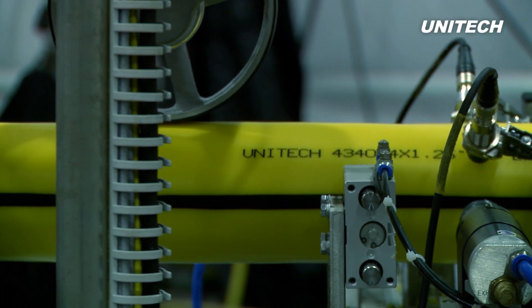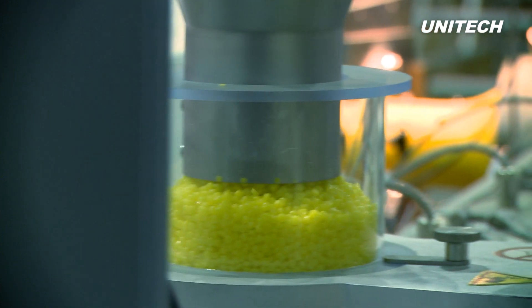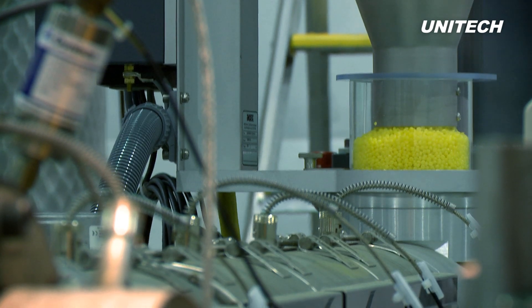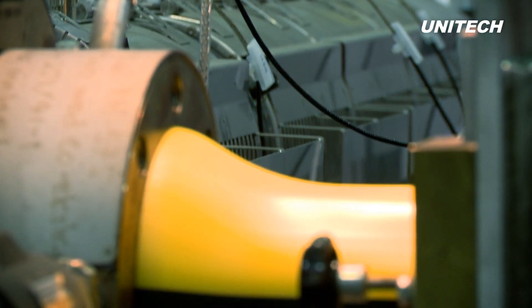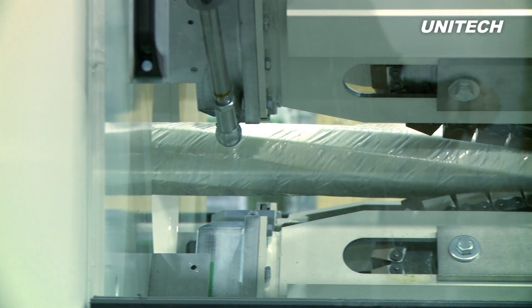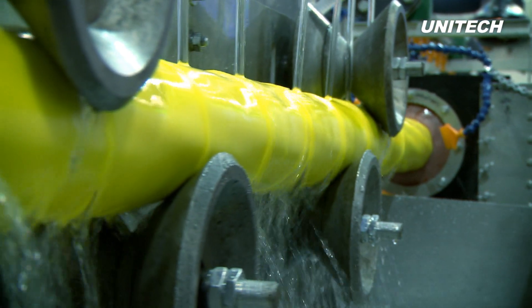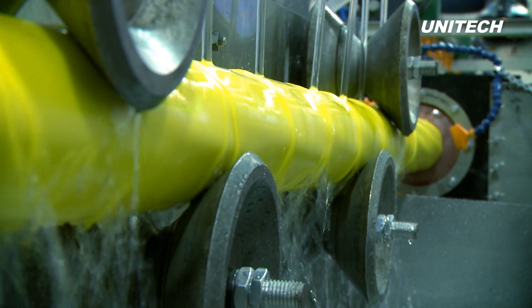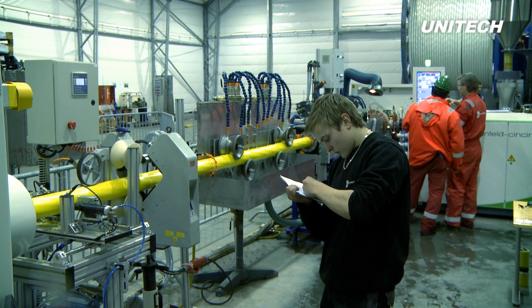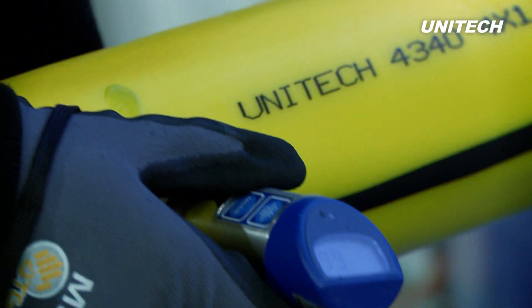The Unitech-installed extrusion line is designed to coat the bundle with an outer sheath of MDPE, medium density polyethylene. The plastic melt pellets are heated to liquid stage with a state-of-the-art and specially designed extruder. While the bundle is running into the molding head, air pressure is applied into the sealed environment. The liquid plastic material is then sprayed on this air stream over the bundle and immediately cooled by water nozzles. The outer sheath can be pricked by a metal sensor-controlled drilling device to allow a fully flooded design.